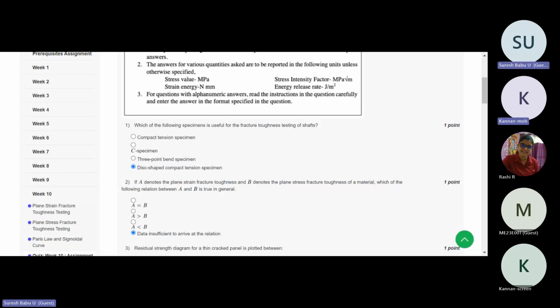Ma'am, for which form of products do you take the 3-point bend specimen? The plate. The sample size is very small, and for thickness and all we follow the ASTM standards. The product I recently did was magnesium. We already have a fracture toughness value for pure magnesium, but we don't have fracture toughness values for magnesium with rare earth elements. So I was doing the experiment based on that recently. And we captured how the cracks are propagating and from where they are propagating, using the 3-point bend specimen.